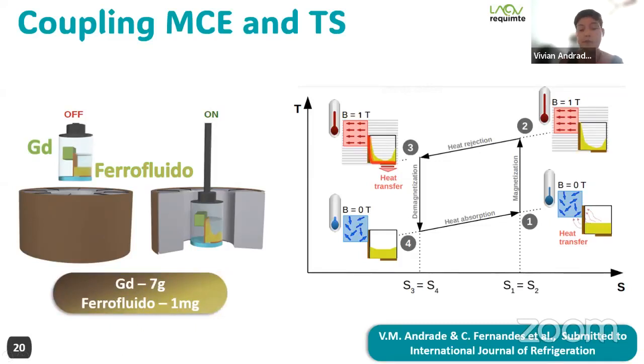So we use 7 grams of gadolinium and 1 milligram of ferrofluid in this device, and we test both ferrofluids, the commercial one and the ethylene glycol based one.